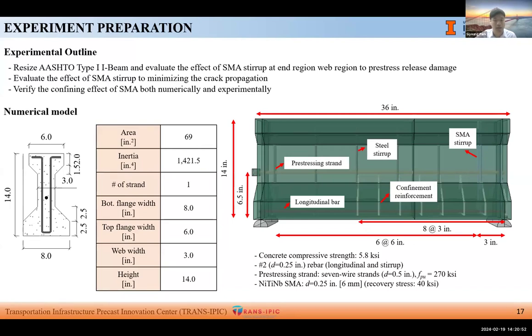Now is the ongoing experimental program that we are working on. To validate the effect of SMA bars at end regions, a scaled-down AASHTO Type I I-beam was set as a reference model, placing a single pre-stressing strand at the web region. Web width was designed to be 3 inches, and pre-stress value was also set as 202.5 KSI. By comparing steel and SMA stirrup models, we are expecting crack mitigation and possibly future load tests can be done.